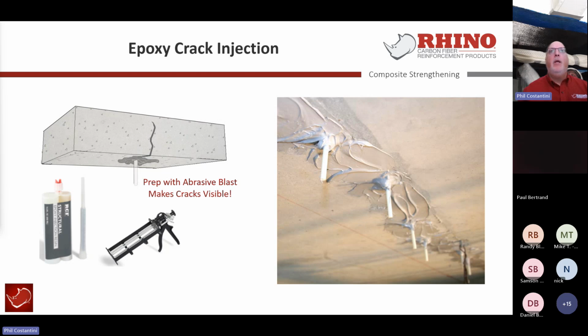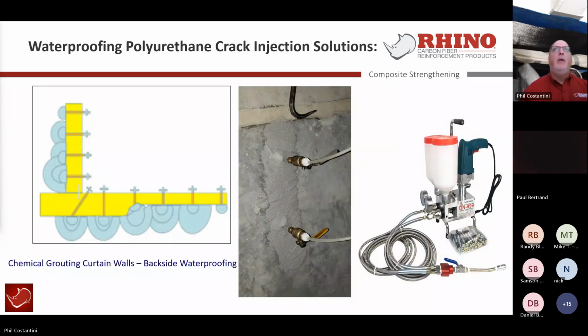Why is that important? You have to structurally bond the concrete back together again. And over the last 30 years, with all the different variations of chemical composition in the epoxy world, that's the best common denominator to reestablish a glue line. What about if it's leaking? Well, we have variations, and Rhino has them, of polyurethane crack injection systems.